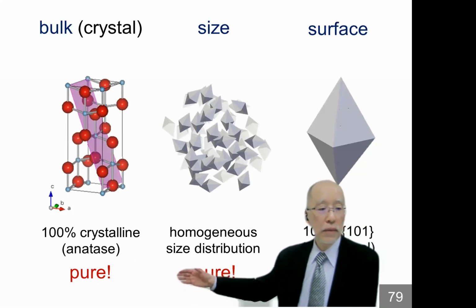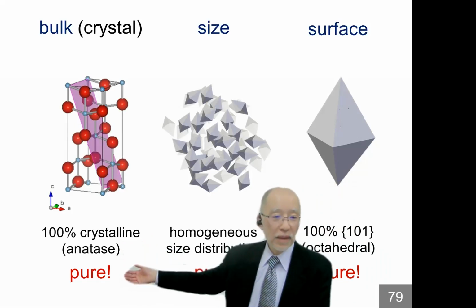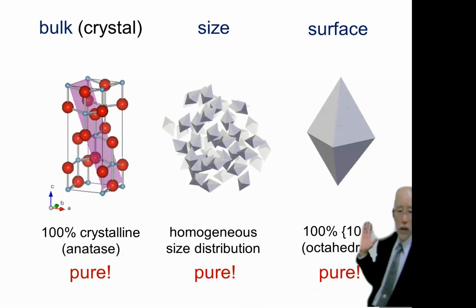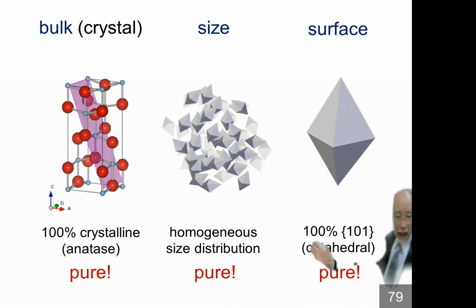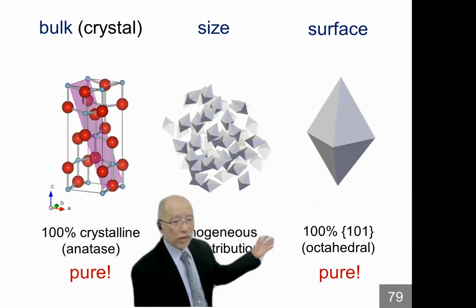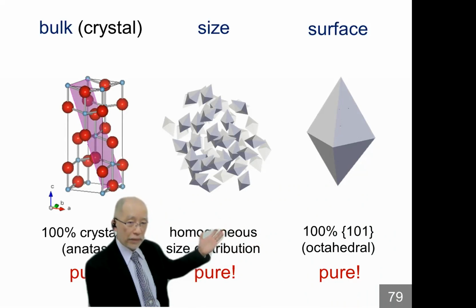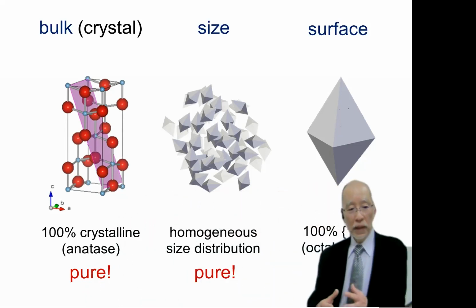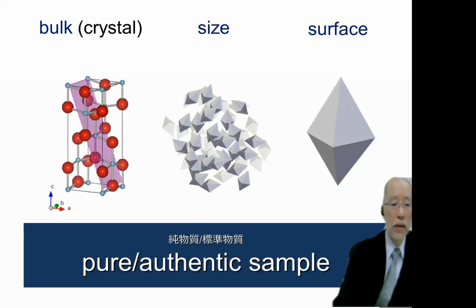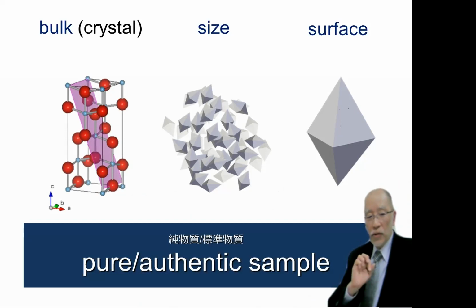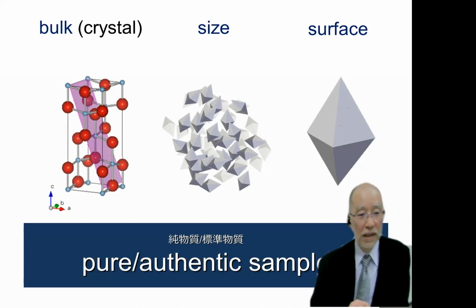Okay, so if the crystalline phase is all anatase, 100% anatase, that can be pure in bulk structure. And if all the particles are of this octahedral shape, they expose only the 101 facet. Therefore, the surface structure can be pure. And if the particle size is the same, with a very small distribution, it is possible to say size is pure. So if we can prepare the same sized octahedral particles, that can be a pure authentic sample. 3 structural parameters: bulk structure, surface structure, and size. All these are pure. So it is possible to say that is pure material.